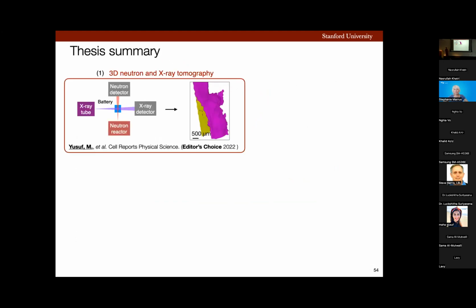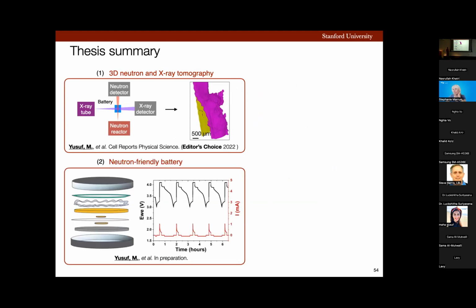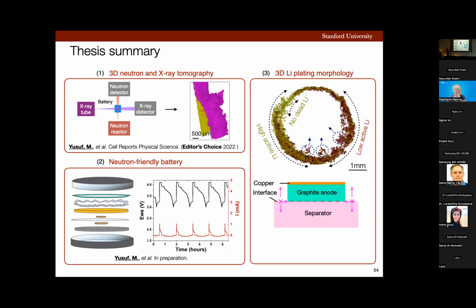To summarize, first, I established the feasibility of simultaneous neutron and X-ray tomography as an advanced characterization method for XFC battery diagnostics. Second, I developed a neutron-friendly battery that is capable of fast charging and enabled us to visualize the graphite-separator interface in situ in a full cell battery. Then I used my developed battery to investigate 3D morphological behavior of lithium plating, where my work has shown that the lithium plating growth mechanism in a real battery is much more complicated than what we know already, where these deposits are left behind and lead to capacity fade of the battery.